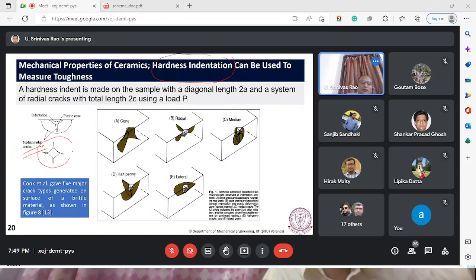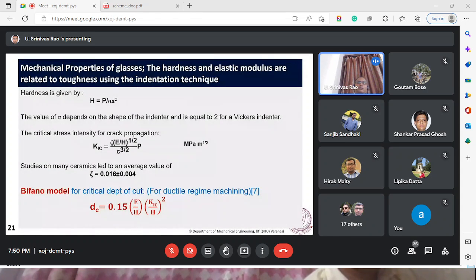Okay, and these cracks can be of these five varieties. So the way it may propagate in different ways inside the material, and what we need to find out is that at what depth of cut or at what critical load the crack is not getting formed. So that is the main essence of further using that information for machining. So load and the length of the crack. Through this experimentation, there is a model developed before now for critical depth of cut.